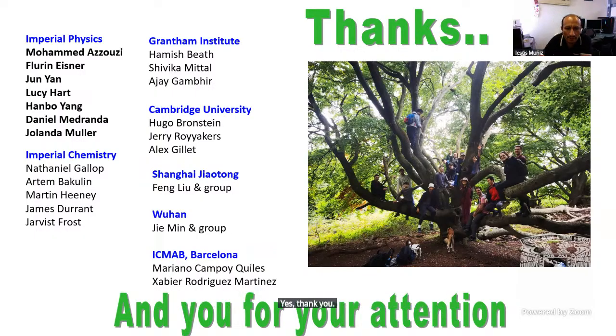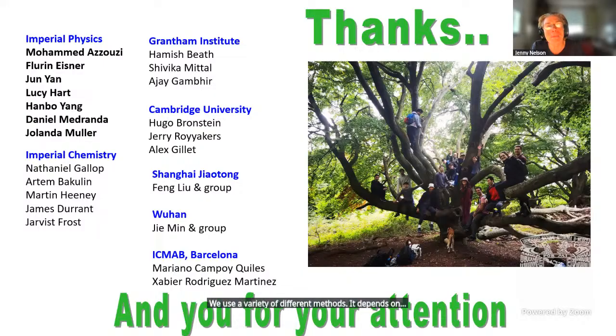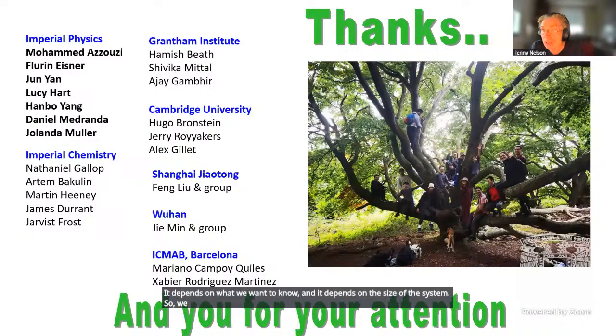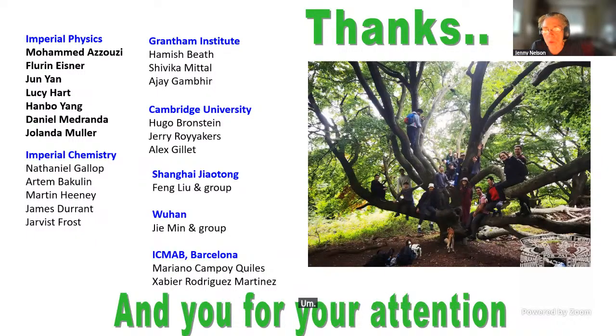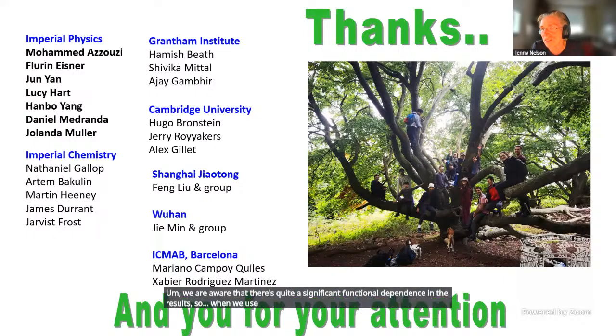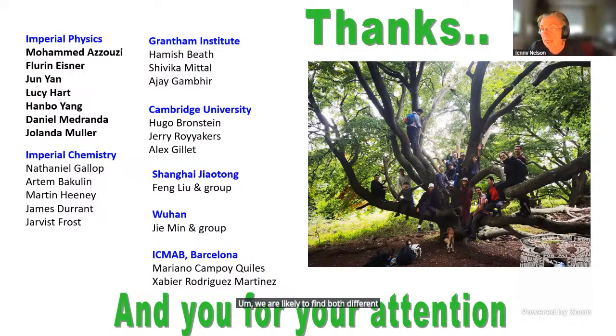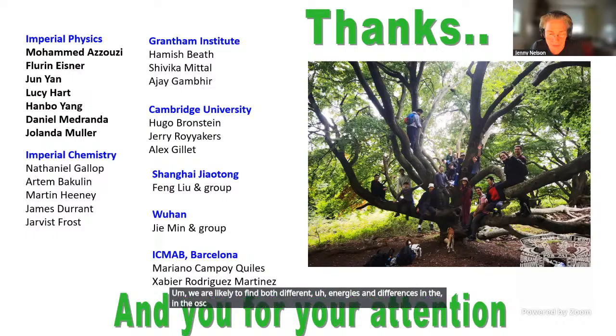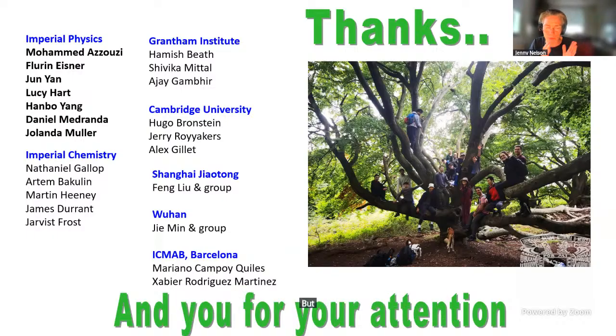Yes, thank you for the question. We use a variety of different methods. It depends on what we want to know, and it depends on the size of the system. So we commonly use time-dependent density functional theory. We are aware that there's quite a significant functional dependence in the results. So when we use different functionals, we are likely to find both different energies and differences in the oscillator strength for the same material. But we're reasonably happy if we're looking at a trend, what conditions will make a state brighter than other conditions. Then we can use density functional theory, and we would repeat it using some different functionals in order to try to make sure that the trend is reliable.